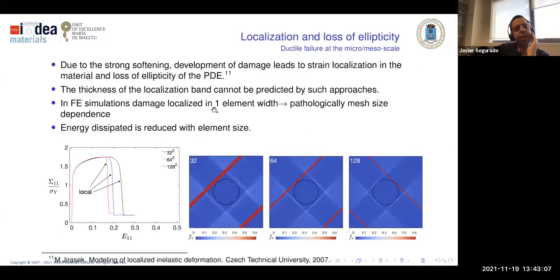And if we put it in an FFT or FEM solver and we study stress strain, we find what we call a localization problem. So the smaller the mesh, the deformation will be localized in very small regions. The size of the region depends on the mesh. So this is mesh dependent, and this is terrible. What can we do to improve this?